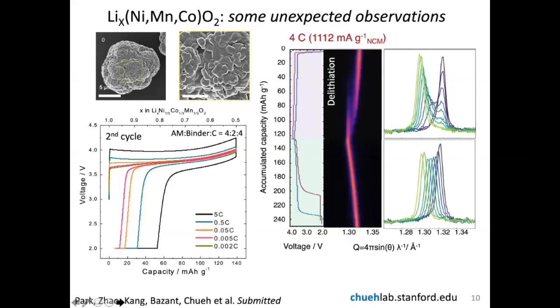But when you start to delithiate at a very high rate, you begin to see something interesting. Here we're delithiating very quickly, at several Cs. You begin to see what appears to be phase separation. You see the coexistence of two lattice constants within the material.